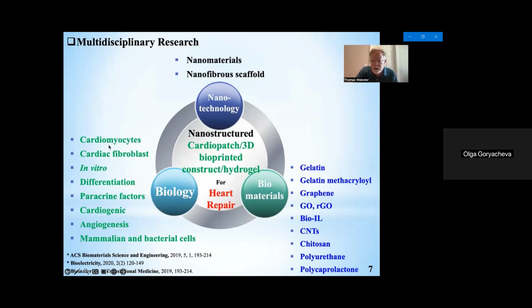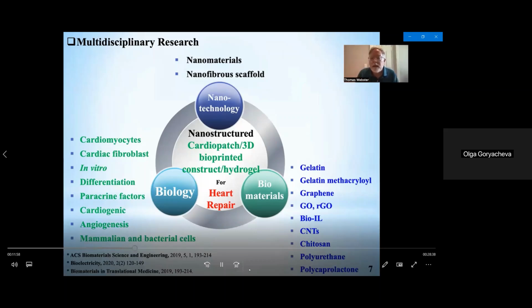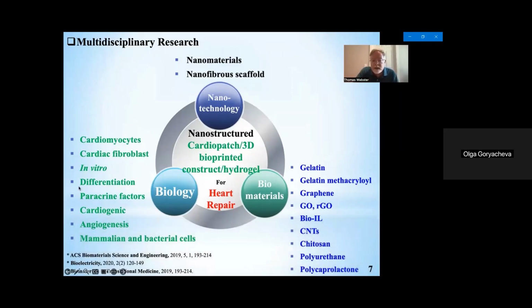We have to be concerned about promoting the adhesion, the migration, when we use these materials alone, the adhesion, the migration, and the function of cardiac myocytes, cardiac fibroblasts. We have done a lot of work, which I'll show you is in vitro, on the differentiation of those cells, and then also looking at paracrine factors that are released from these cells to stimulate other cells to regenerate natural heart